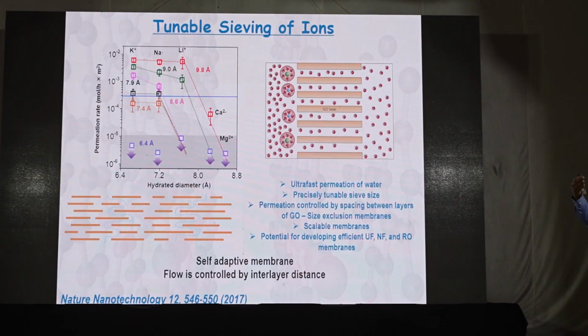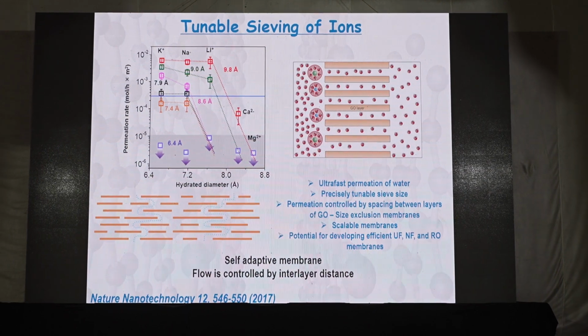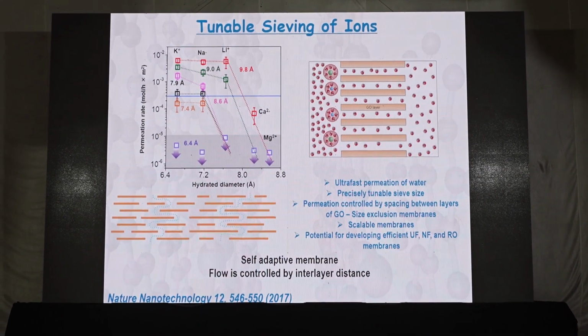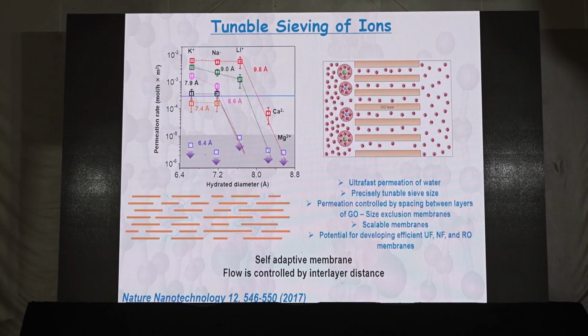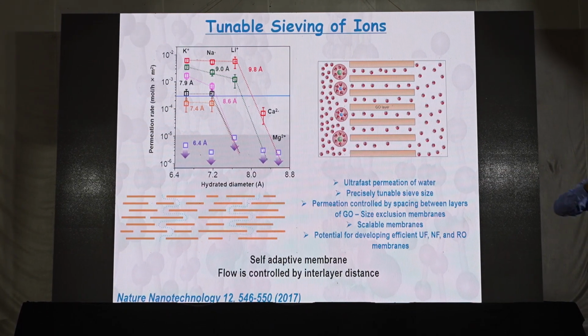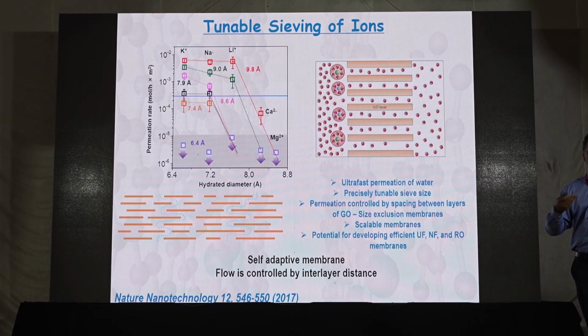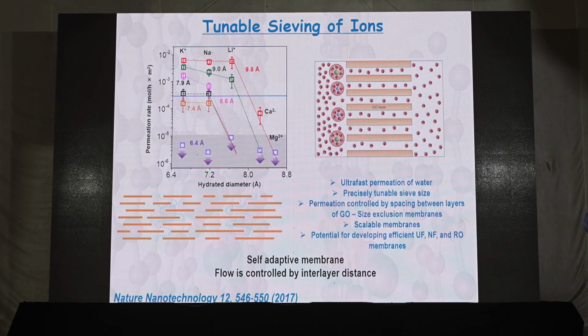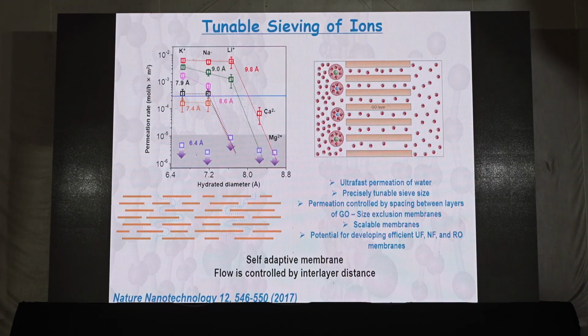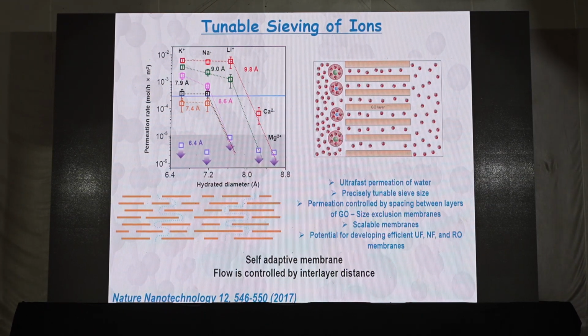Anything less than around 8 angstrom, you get passage of water, but the same membrane blocks sodium chloride. It's not completely blocking, but the ratio between water and sodium chloride is very high, so that you can get more than 99% removal of sodium chloride from water. So it works like this.